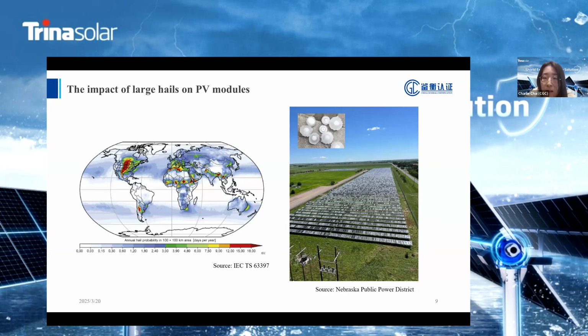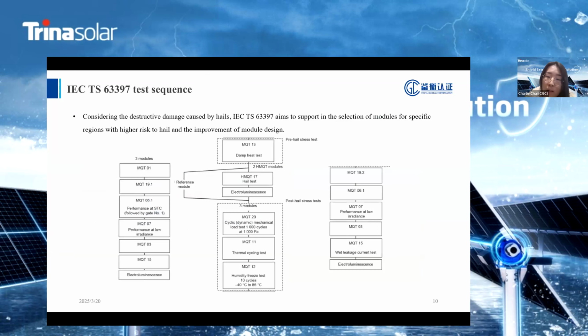Right picture is a real case of a solar farm in Nebraska, which suffered significant hail damage. This project features double glass modules and utilized single axis trackers. Based on visual inspection, the glass of most solar modules was damaged after hail. Moreover, those that appear to be good might get micro cracks, which then reduce the panel power output. Considering the destructive damage caused by hail, IEC TS 63397 aims to support the selection of modules for specific regions with higher risk of hail and the improvement of module design.